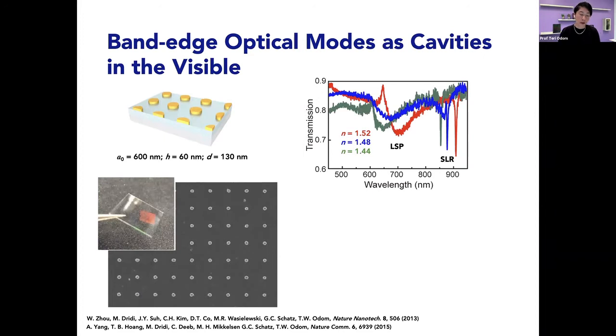So this is an electron micrograph and an optical micrograph of what these lattices look like. These are just typical array parameters. So we typically pattern about a centimeter squared area. And these are some of the properties. So this is the SLR, this is normal incident transmission. This is the lattice interacting all together. You can see that the resonances are very narrow. And you can also see that these also support a localized surface plasmon resonance, and these are characteristic of individual particles in the lattice. So it's really nice.